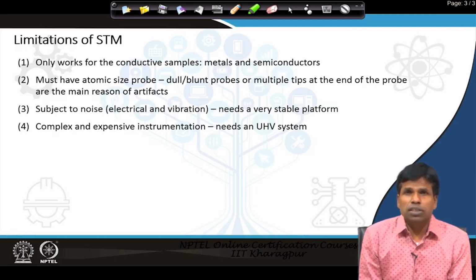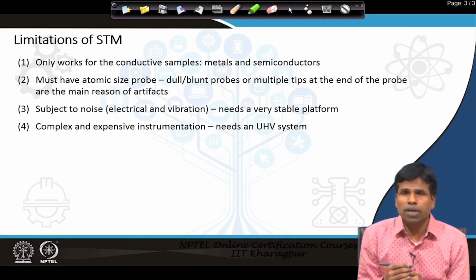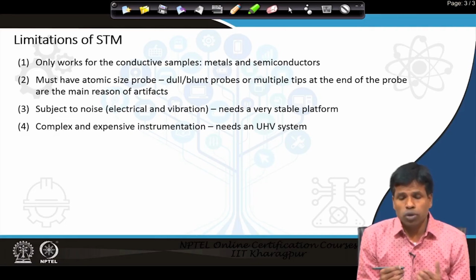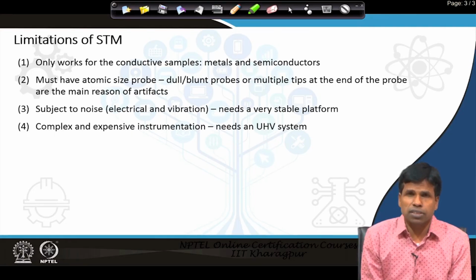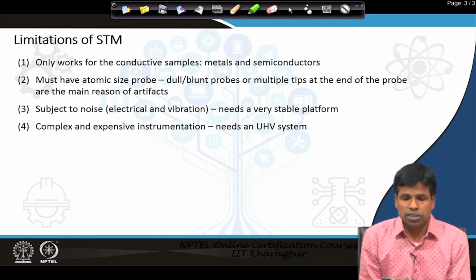Moreover, as we measure the tunneling current, and the tunneling current can only be measured when the tip and sample are brought very close to each other, at a distance of a few angstrom, we should have complete vibration isolation. Any type of small vibration cannot be acceptable to get information at the atomic level. So, one of the issues is that it is subject to noise.